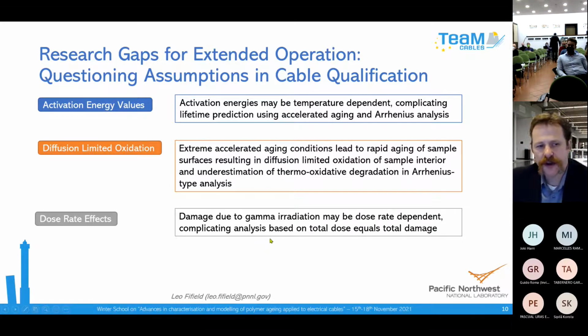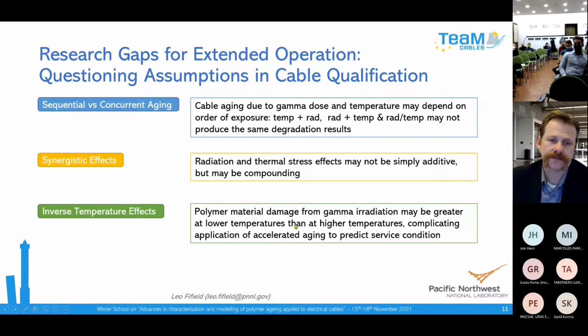Okay, the next assumption is dose rate effects. Like I mentioned, 50 megarads, or 500 kilogray, was assumed as the dose over 40 years during qualification. That was often applied all at once at a high rate, like 1,000 gray per hour or more. And the question is, when you apply a total dose over a few hours versus over a low dose rate, maybe 10 gray per hour or 1 gray per hour over many years, do you get the same degradation mechanism? So that's a dose rate effect.